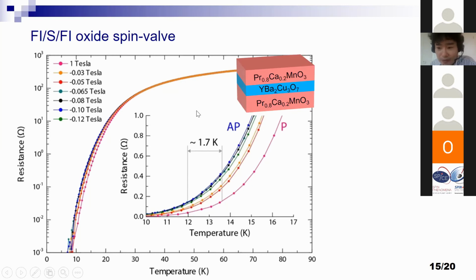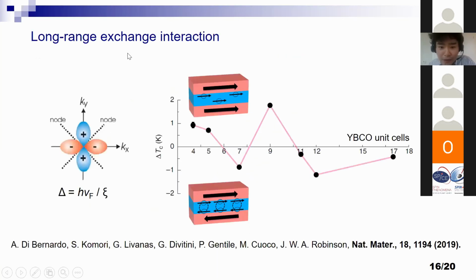So this 1.7 Kelvin is kind of the biggest TC shift we can get from this kind of FSF spin valve structure. And this coupling, exchange coupling, is quite strong. And this effect, TC switching, survives up to about 20 unit cells of YBCO. So this is TC switching as a function of YBCO interlayer thickness.